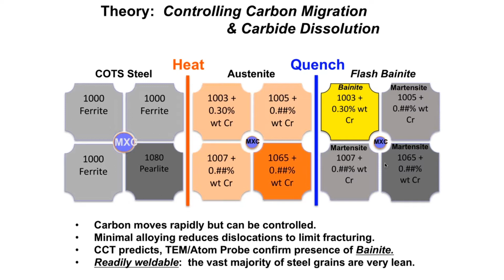The reason this may have been overlooked in the past is because 1003 plus 0.3 chromium is not the first alloy you'd think of as having a useful commercial value. So we state that carbon can move rapidly, but it also can be controlled. And you can do this through a thermal cycle, which is very easy to ingrain into a piece of mechanical equipment. We do have very minimal alloying, so it reduces dislocations and limits fracturing. As I mentioned, we do know bainite is there.